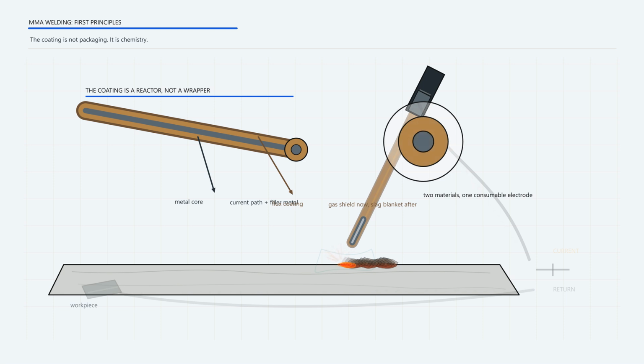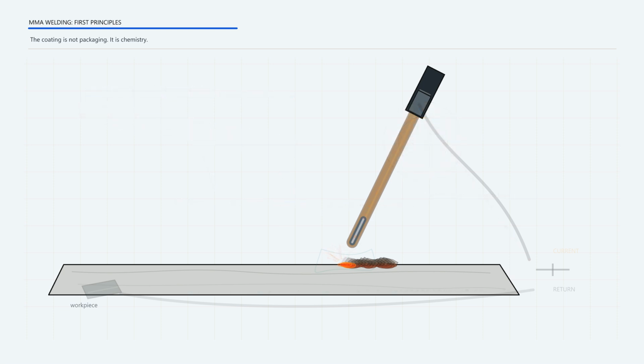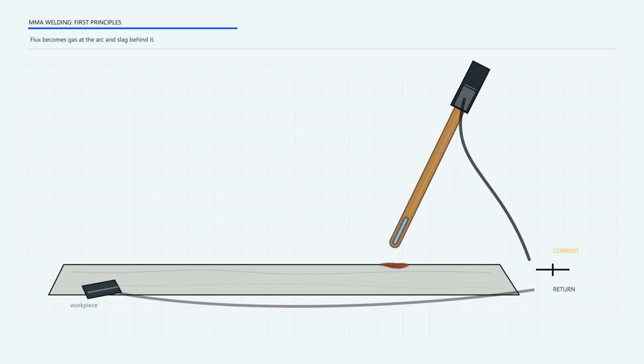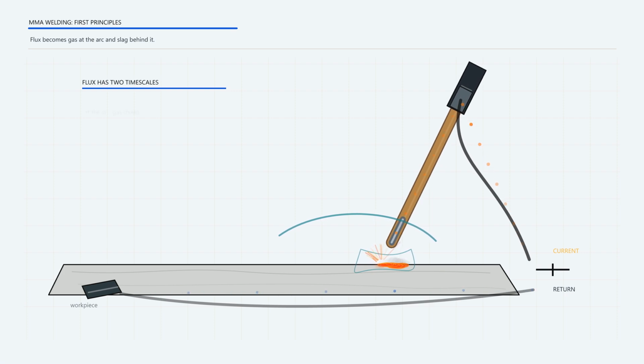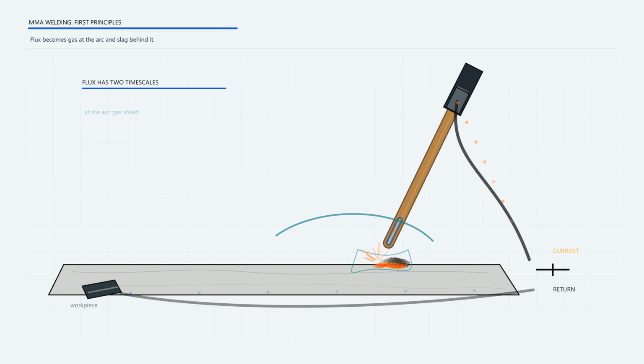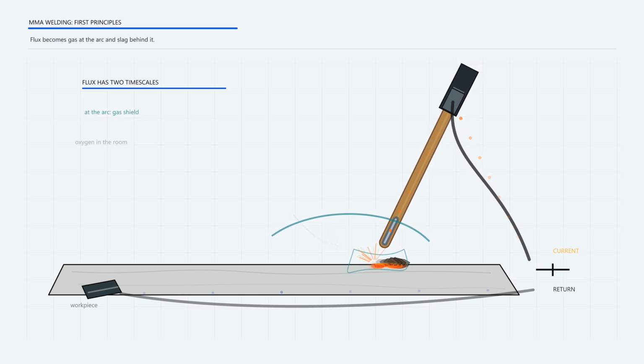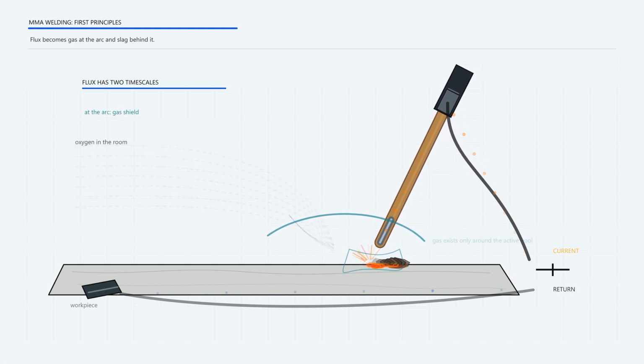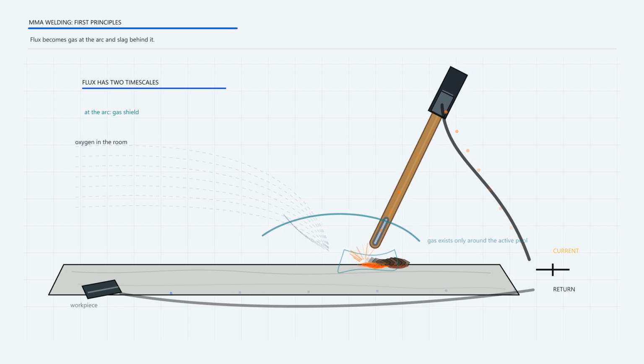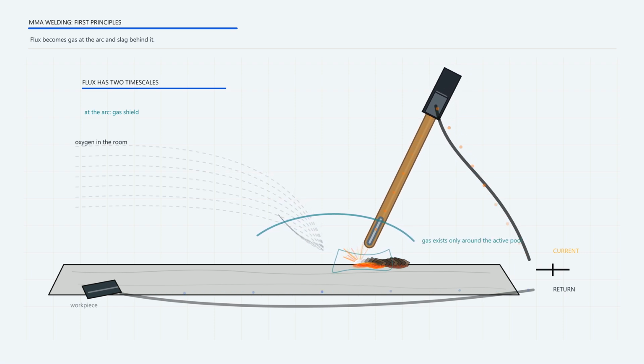Behind the arc, a second protection layer takes over. Molten slag floats on top of the bead because it is lighter than the weld metal. It slows cooling, blocks air, and shapes the surface while the bead is still hot. Later, after it has done its job, the slag has to be chipped or brushed away. This is why manual metal arc can work without a separate gas cylinder. The protection is born at the arc. The gas cloud pushes air away while the metal is liquid. Behind the arc, molten slag sits over the bead like a temporary glass lid.